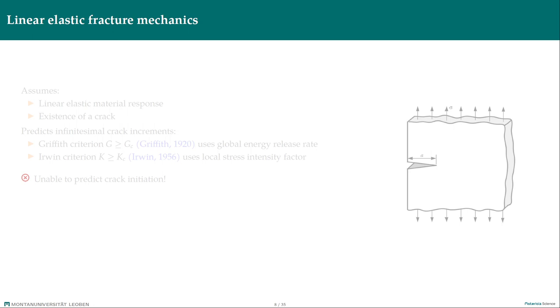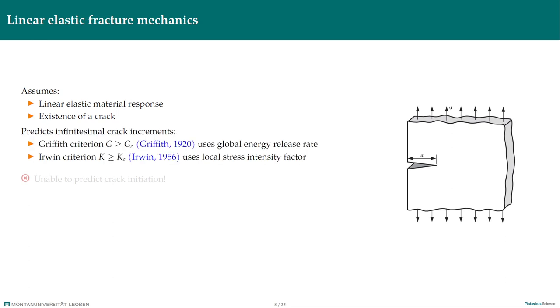The classical fracture mechanics assumes a linear elastic material response and it requires that a crack is present. It can tell us if the crack will propagate further by an infinitesimal increment. Either by fulfilling the Griffith criterion which states that the energy release rate or crack driving force must be greater than a critical value or equivalently by fulfilling the Irwin criterion for the close vicinity of the crack tip which states that the stress intensity factor must be greater than the fracture toughness. Nevertheless, we cannot tell if the crack initiates. Hence, let me introduce you to a concept of finite fracture mechanics.